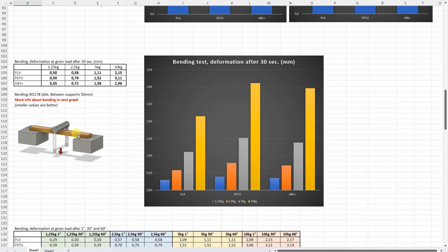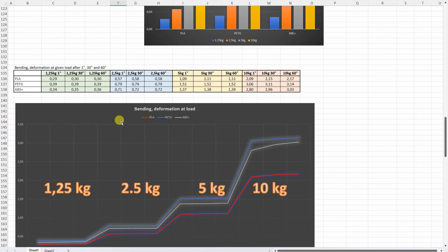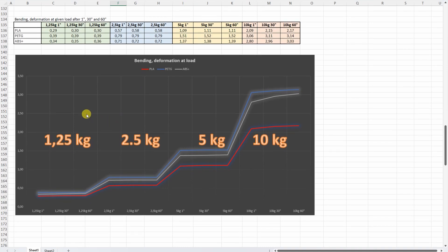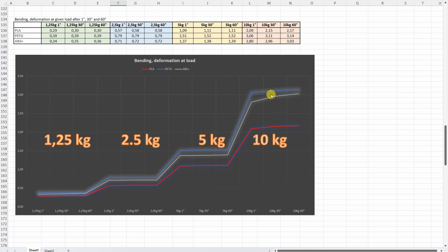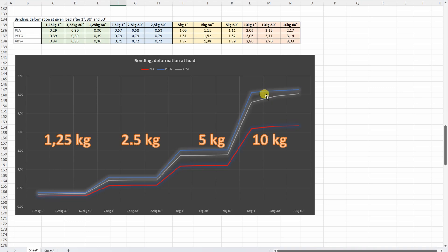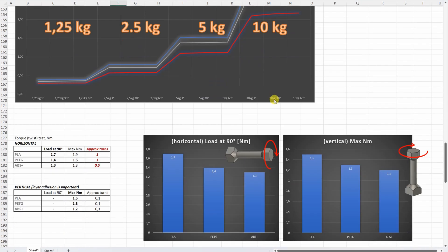Three-point bending test—here you can see the deformation after 30 seconds under these loads. But maybe this graph is more interesting where we can see the deformation after 1, 30, and 60 seconds under these loads. Smaller values are better of course. We can see that PLA is a stiffer material, then ABS and PETG. But very interesting—I don't really understand this at 10kg. With the ABS I can see some short-term creeping. So in this case I prefer the PETG compared to the ABS. Usually I see opposite directions of the graphs.